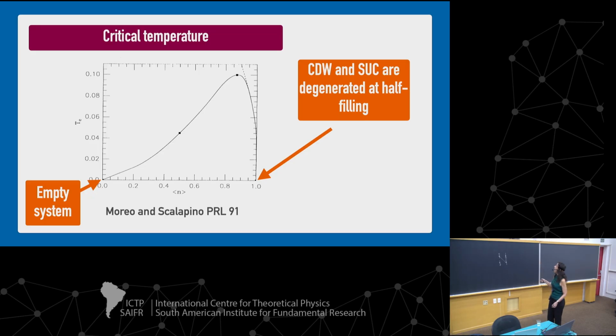And here, what happens is the charge density wave and the superconductivity are degenerate. And so they add together, they have 3 components, and this drives the critical temperature to 0.